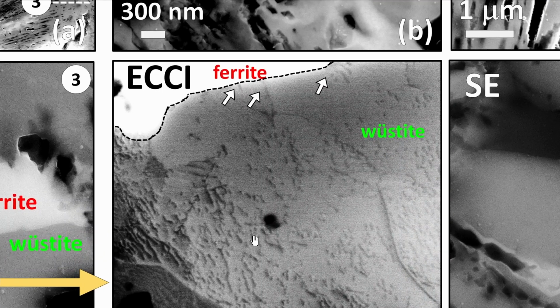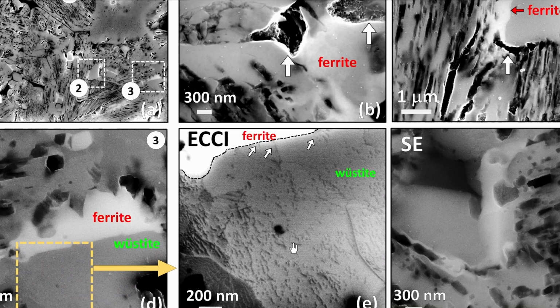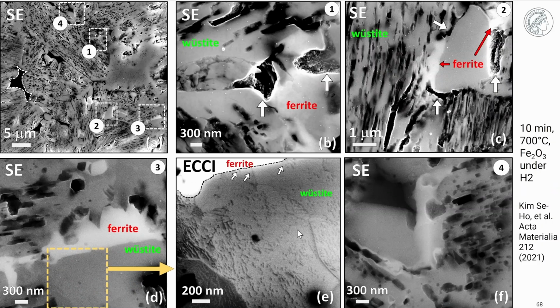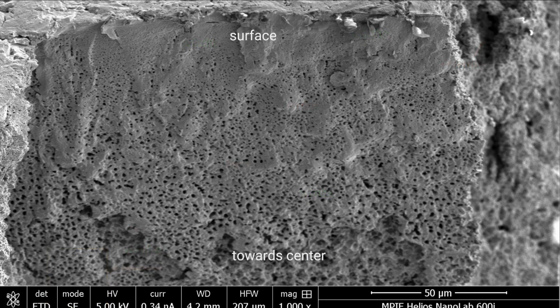And here you see, even in the electron channeling contrast imaging, that very complex dislocation substructures form. This has to do with the fact that these different oxide states and also the metal states occupy very different volumes, which gives rise to the fact that you do not only form massive pore structures during the reduction, but you also build up very high stresses.